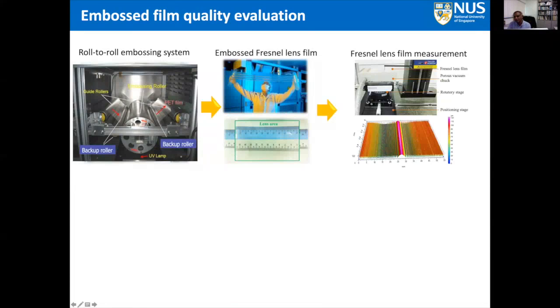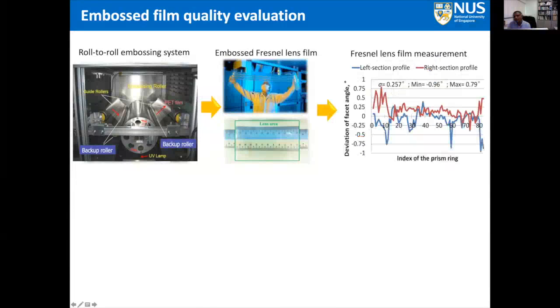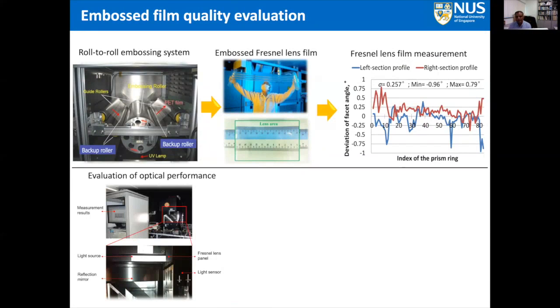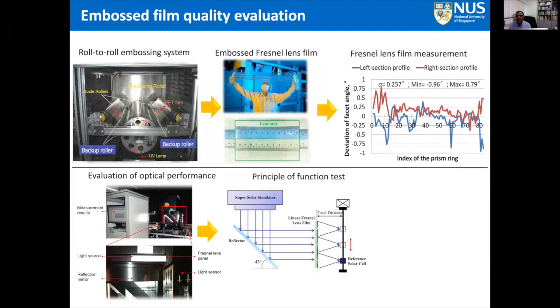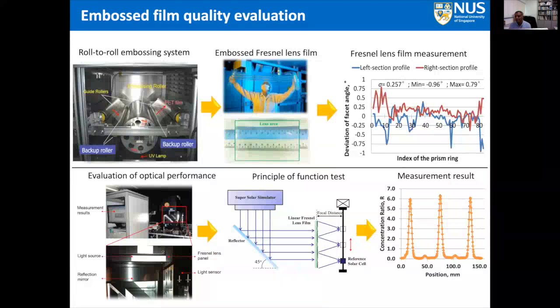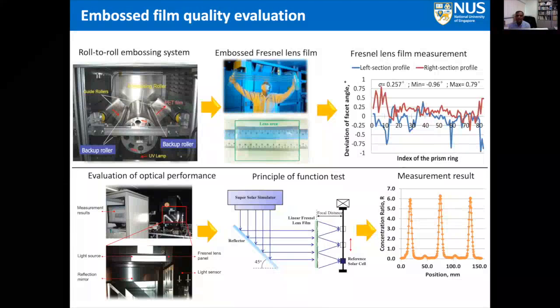And we also do characterization of the Fresnel lens by using, again, measurements. After we do the PET, we also do the measurements using the stylus profilometer to see the deviation of these angles. And what you see here is the actual measurement, which is less than 1 degree. And also we do some optical performance evaluation, and we see the concentration of these lenses using the super solar simulator. Then we use the cameras to detect the phase at the focal point and then see how the intensity is. And of course, you observe that the intensity is relatively very, very high compared to that of a normal flat film. Okay, so it has a definite improvement in terms of the application. So we use these techniques in our machining and for industrial applications as well.